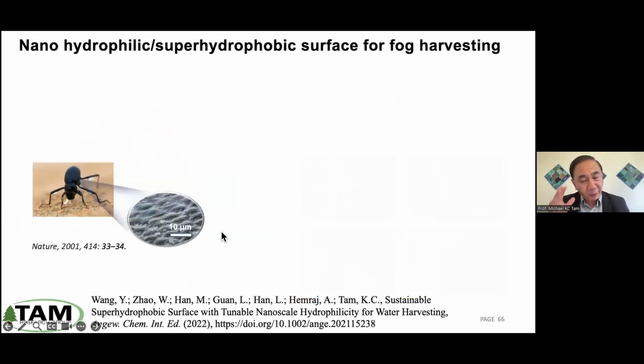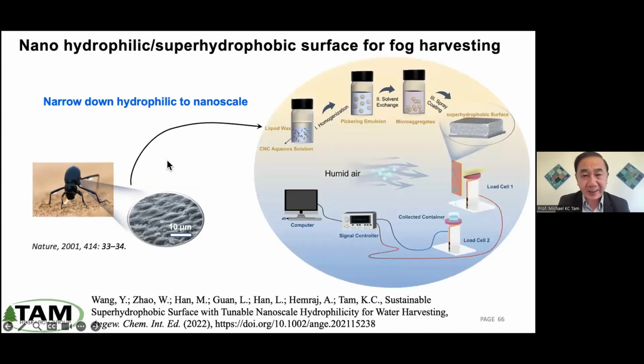So we are trying to imitate, or to look at, in this case, a desert beetle, how they're able to capture water and harvest it and bring it to be consumed by themselves. So we take this wax and the CNC and we emulsify, make the wax droplet, and then we do a solvent exchange and spray coat it onto a substrate.